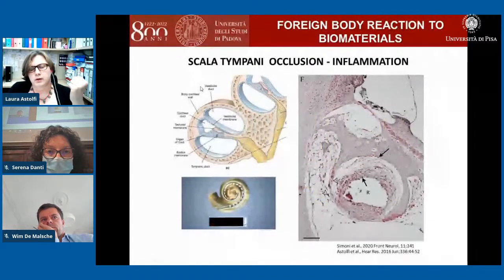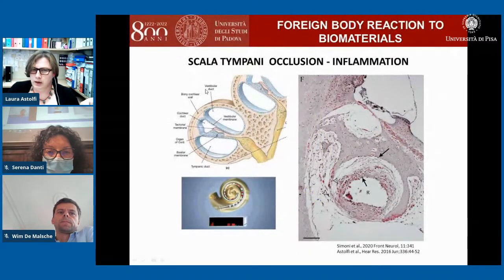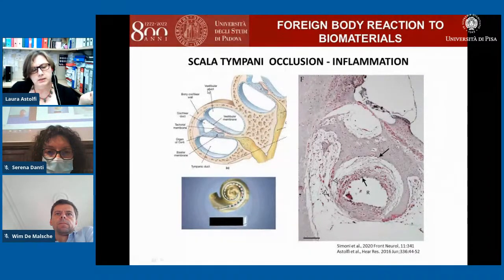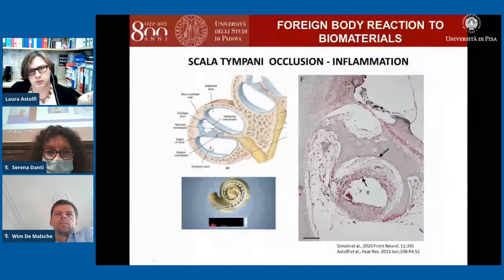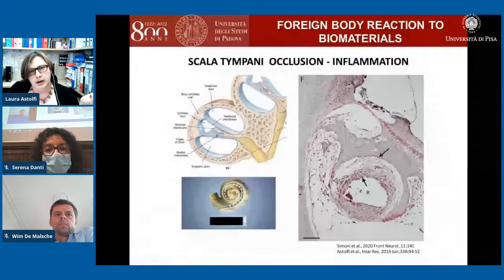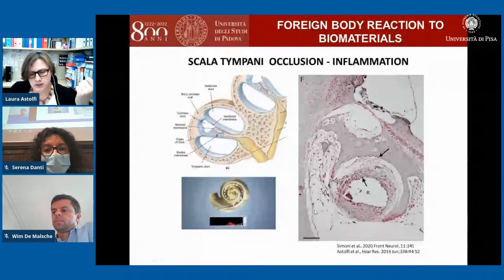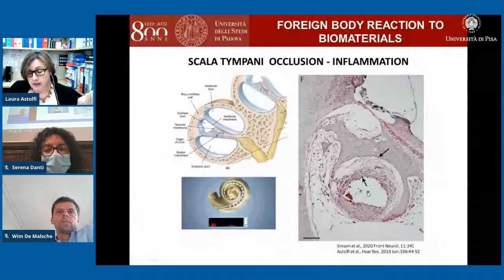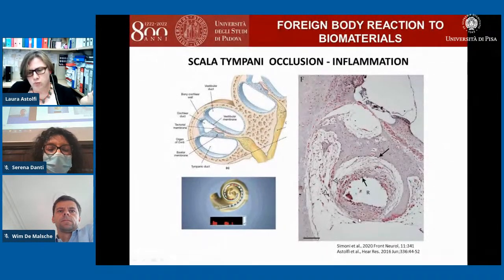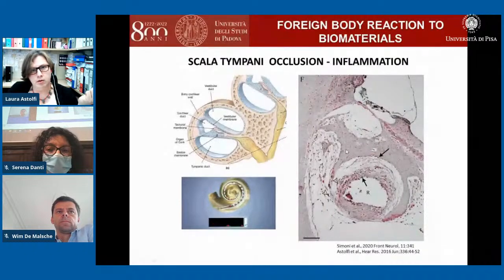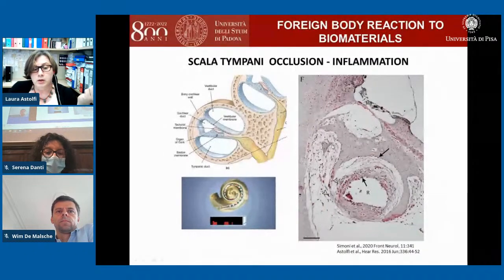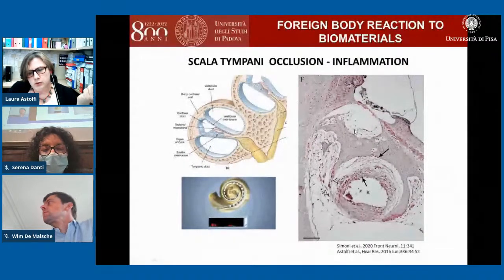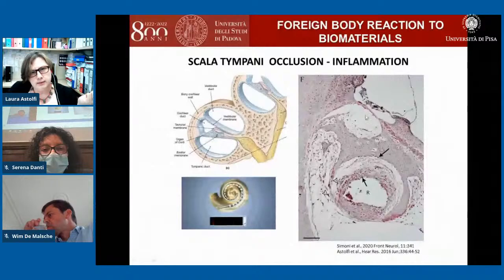Another issue of the cochlear implant is the impedance of the electrode, because when we insert the electrode in the scala tympani, since it's a foreign body, we have the foreign body reaction. So we have tissue growth around the electrode. This is an example of an experiment in which we put a silicone rod inside the scala tympani, and as you can see, after 2 months we have all this amount of tissue growth around it, and so we lose the possibility to stimulate the basilar membrane.